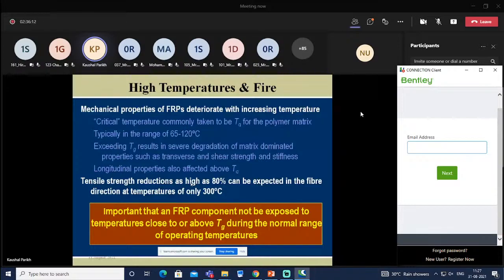And when the bond is damaged, the purpose for which the FRP is applied for retrofitting and strengthening cannot be served. Tensile strength reductions as high as 80% can be expected in the fiber direction at a temperature of only 300 degrees centigrade. And when there is a fire, this type of temperature is definitely reached within a very short time. So it is important that the FRP component not be exposed to temperatures close to or above Tg during the normal range of operating temperatures.